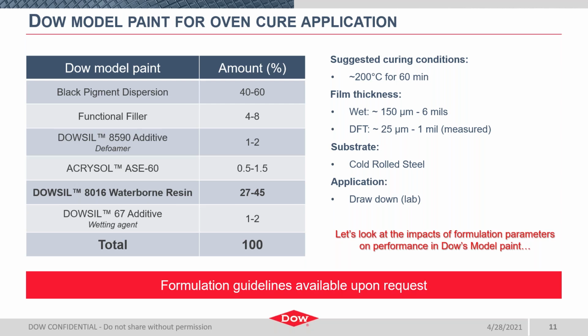Of course, you can include other fillers. For example, you can include other reinforcing types, or you can include carbon black at low levels if needed. I've seen this included for jetness or color specifications, but it's not going to be a recommendation as carbon black doesn't really add to silicone resin function or performance. And then the additives in the formulation include 8590 additive as a defoamer, the DOWSIL 67 additive used for wetting. This further helps eliminate the need for coalescing solvents. And ACRYSOL ASE-60 is the rheology modifier we've developed into this formulation. It's recommended at a very low level, which again is common for water-based paints.